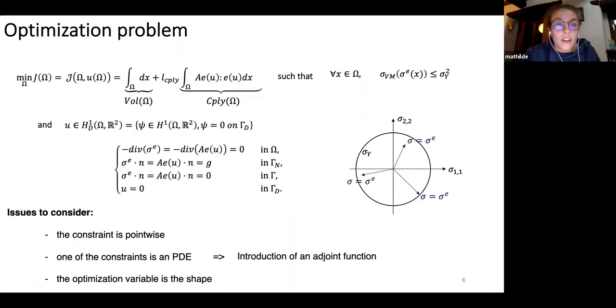And then with this formulation, we get an optimization problem. So in this work, what we want to optimize is the weight. We want to not use much material and to get something as light as possible. The compliance is only here for a stability reason, so I will not talk much about this compliance here. And we have also the constraint that we don't want any plastification. So at each point of the shape that we have designed, we want to make sure that the ideal elastic stress satisfies this inequality. And we still have U, which is the elastic displacement. So basically, that's the optimization problem. And then with such an optimization problem, we have three different issues.